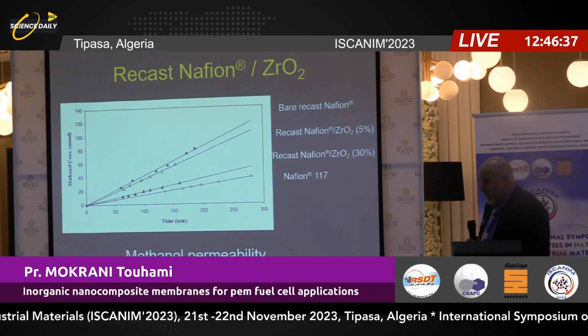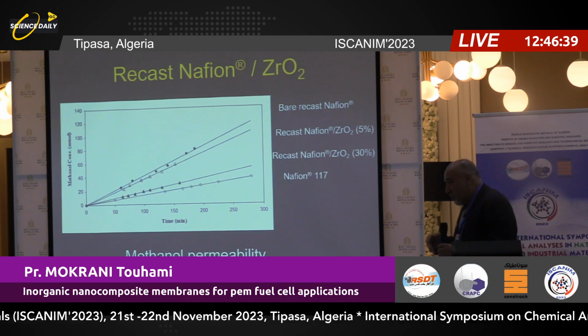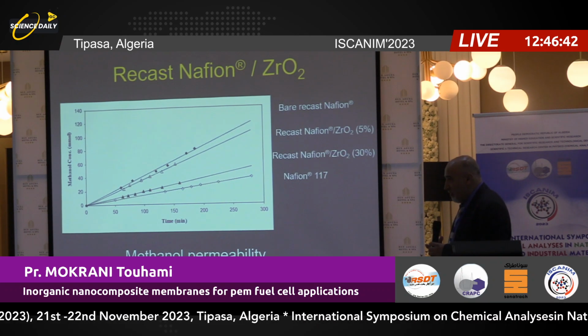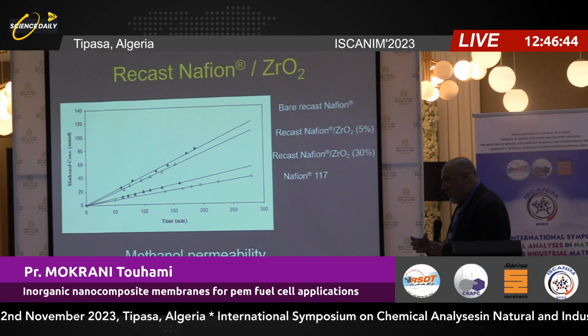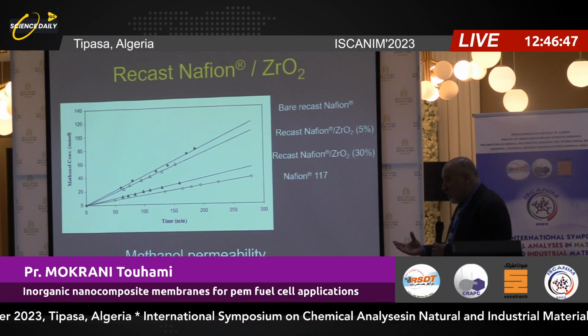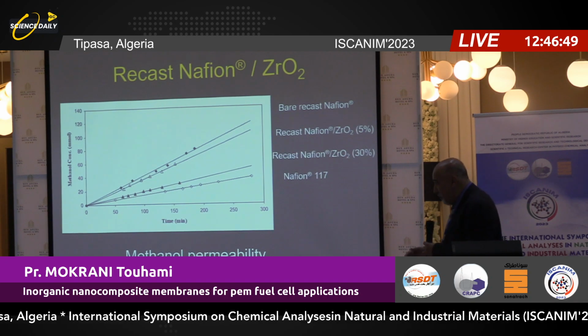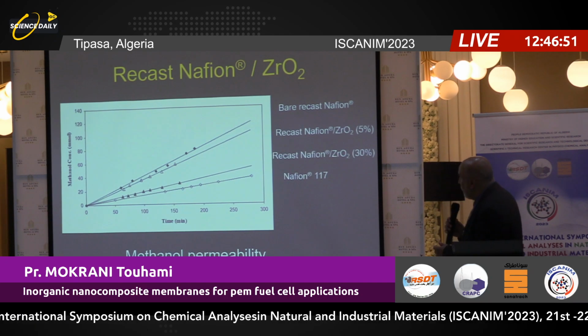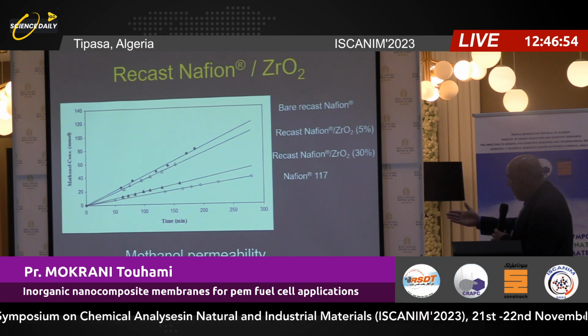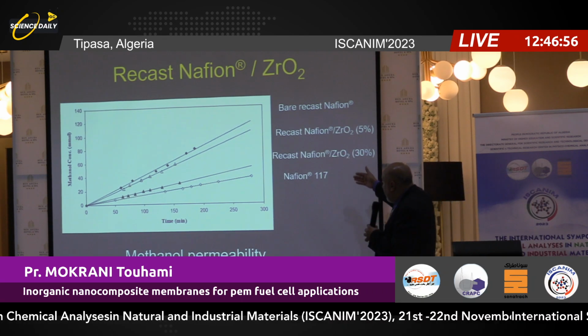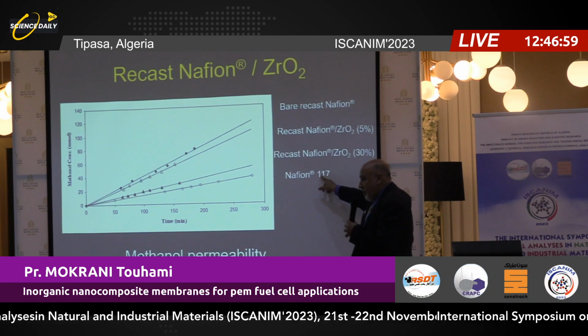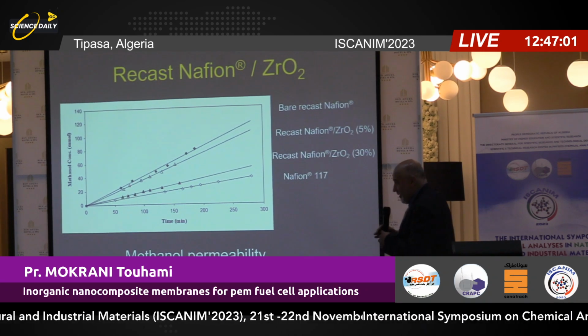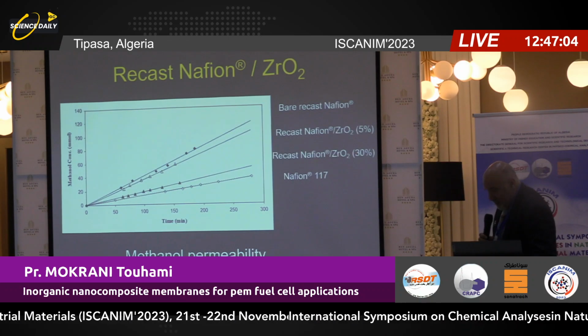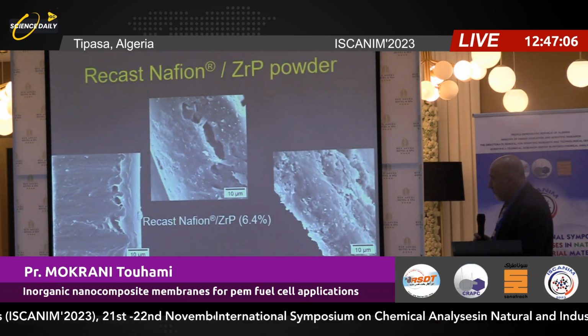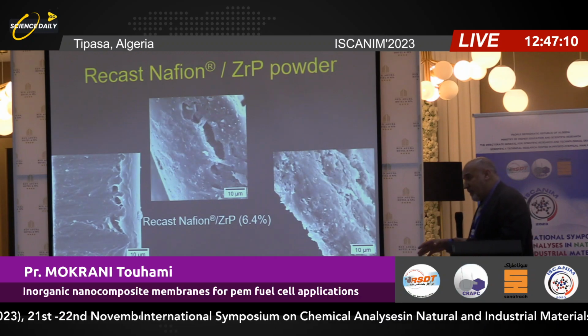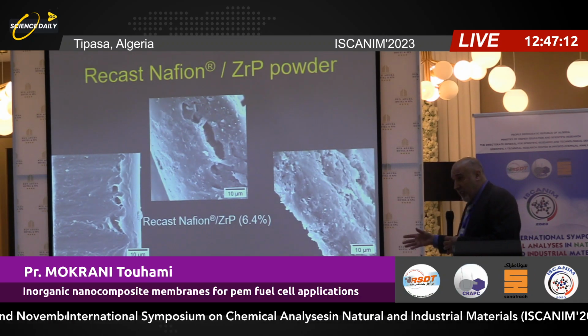So all the time, as I am saying, it's a balance. So you need to understand your materials, how they behave. And you take the balance, and any disadvantage you try to overcome somehow. This one is recast Nafion zirconium oxide. We see the methanol permeability. So in this case, all of them are worse than Nafion, because Nafion is the lowest. But that doesn't mean that it's bad, because all the time there is something else we are going to win on it.